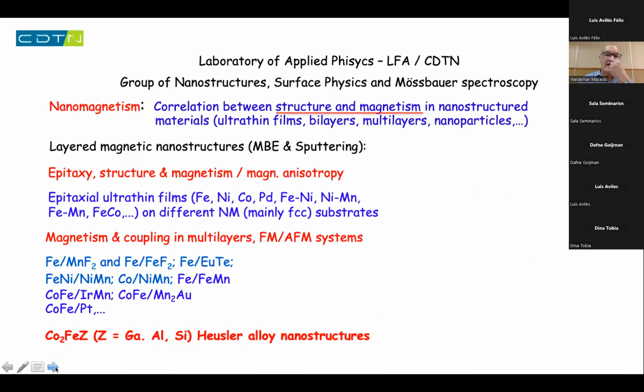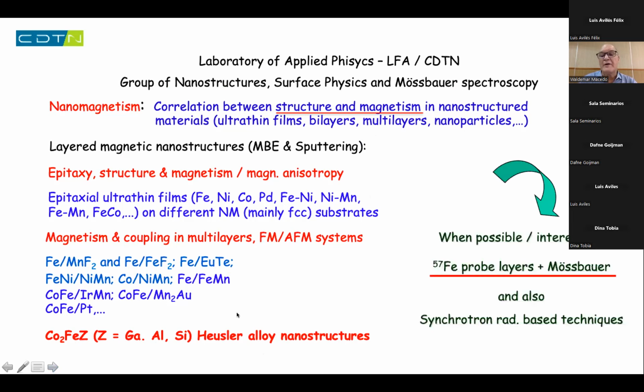Okay. In our lab, what we do in nanomagnetism, I've been studying the correlations between structure and magnetism: how, when you do epitaxy, you can play with the strain or the lattice parameter of the materials, and how it changes the magnetism of different systems. We also study exchange bias, and right now we are interested in nanostructures of Heusler alloys based on iron, cobalt and iron. And always, when possible, we use the iron 57 probe layers approach and synchrotron radiation to investigate our systems.